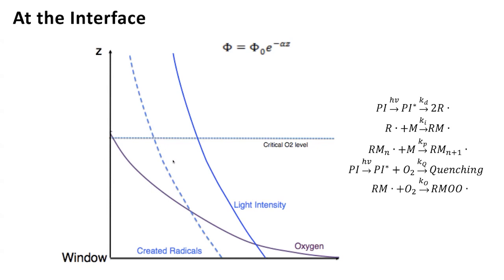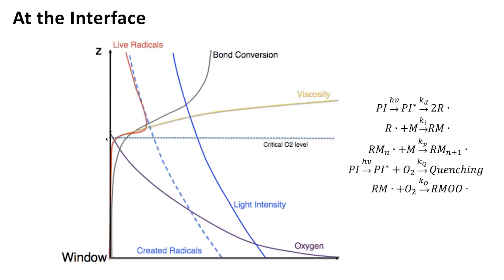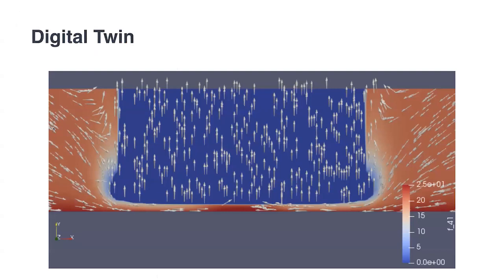So what's happening is the photoinitiator is consuming the oxygen, but the oxygen is being replaced asymmetrically at the window surface. And so the oxygen concentration is high at the window, and it's decreasing with distance up into the liquid like this. Once the oxygen concentration gets below a certain threshold, then polymerization will take place, bond conversion goes high, viscosity goes high, and there's this polymerization gradient. And there's this gap that we call the dead zone. It's this dead zone that allows resin to be pulled in underneath the part.